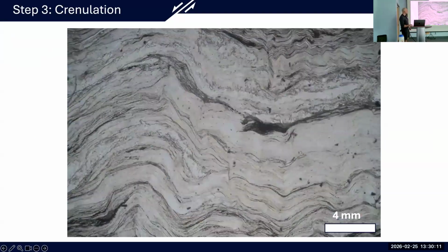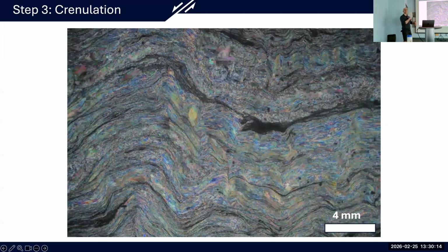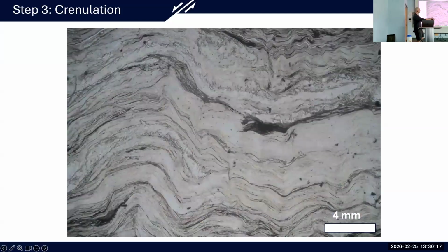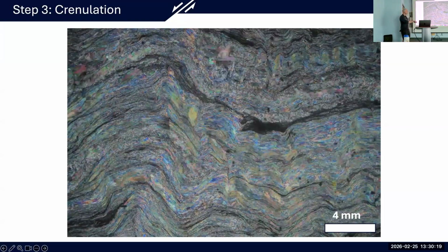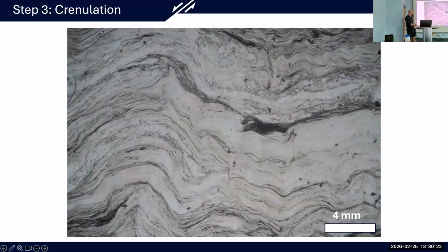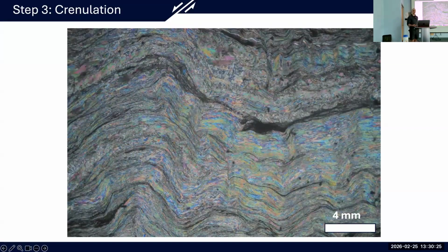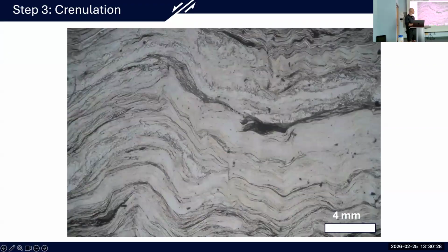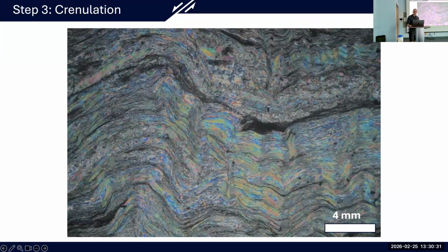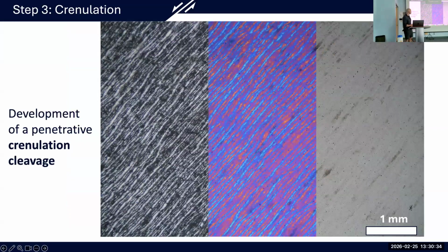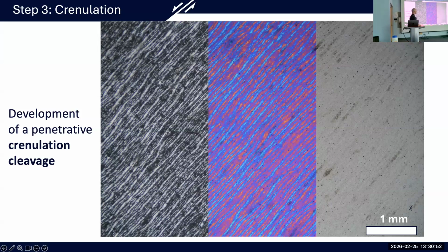Here we have a cross-polarized image that's sort of cycling through with rotations of the polarizer. And you can see that our layers are buckling, and this folding, which is pervasive and penetrative through the sample, is our crenulation. And if we allow this to progress under those sustained stress conditions, we can form these rather remarkable rocks which have what's known as a fully penetrative crenulation cleavage. So these lines here, we're looking at a cross-polarized image with a retardation wave plate giving us a 90-degree phase difference and a plane-polarized light image.